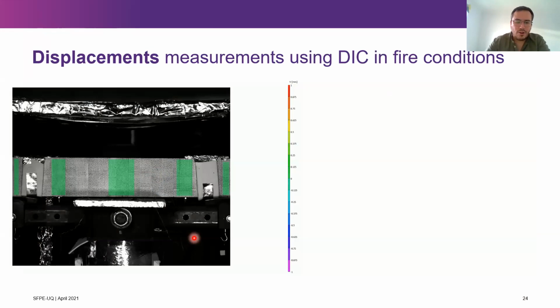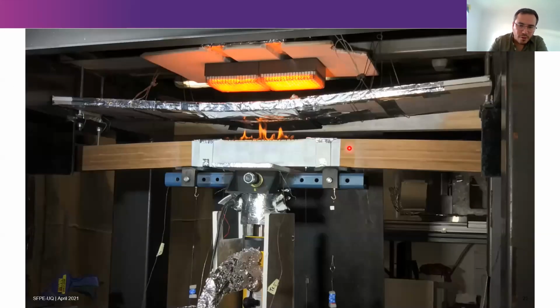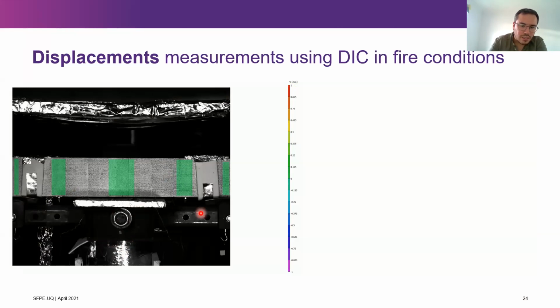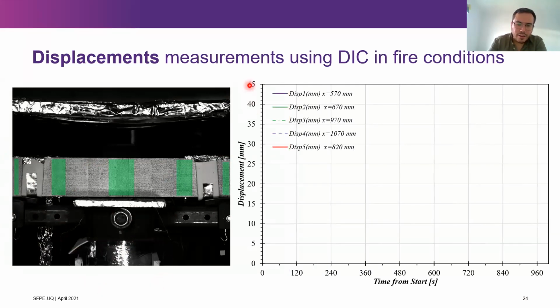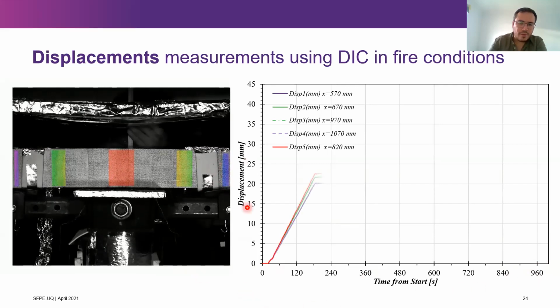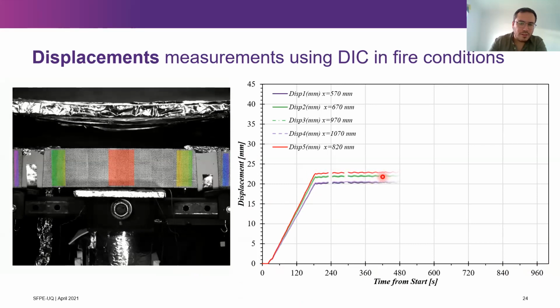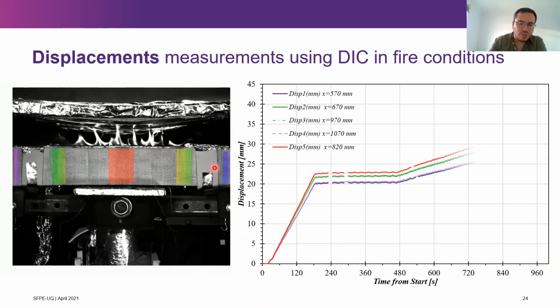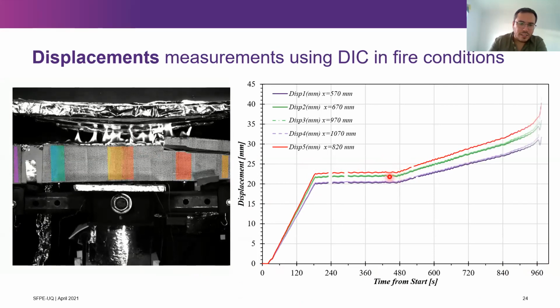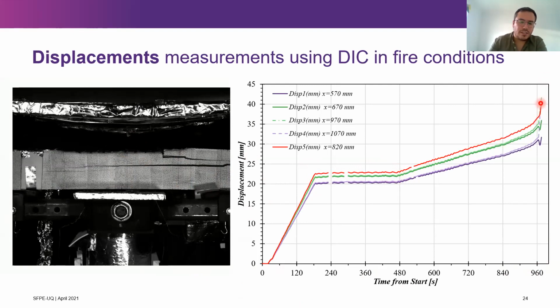One of the more innovative approaches in this test setup was the use of the DIC in a fire application. What you will see here is a zoom in of the middle third of the beam. Again, you see the actuator, the load cell, our transfer beam, and the central third of the beam. Here you have displacement against time. We start loading the beam until we reach the desired stress level, and then at that point, we start the fire exposure. You see that the beam starts increasing the displacement until it finally reaches failure.